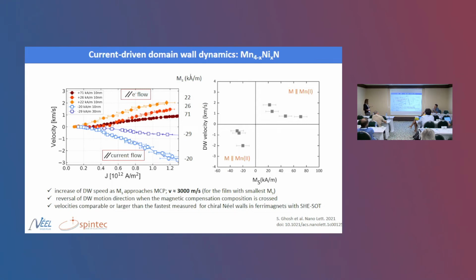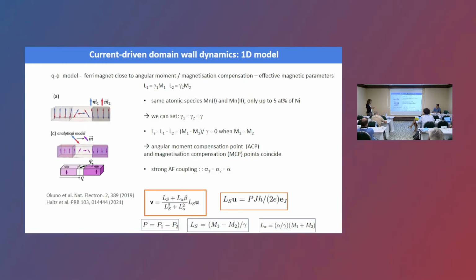And then, okay, so we were happy to see these large velocities that are actually comparable or even larger than the fastest measured in ferromagnets driven by spin-orbit torque. So in order to explain these results, we considered the collective coordinate model that was adapted to a ferrimagnet close to angular compensation.